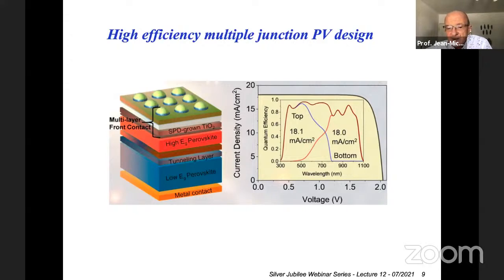They are a little bit tricky to engineer because the so-called tunneling layer, which is here, requires some attention. It depends really on the different materials that you stack on top of each other, understanding that these are wet processed. So there is a need for compatibility of the different solvents that we are using. So it's not so simple, but it is doable, and it allows us to reach high efficiency. And again, by modeling, you can predict which efficiency and which thickness of the layers you need to use to design the material and the solar cells, which is very important.